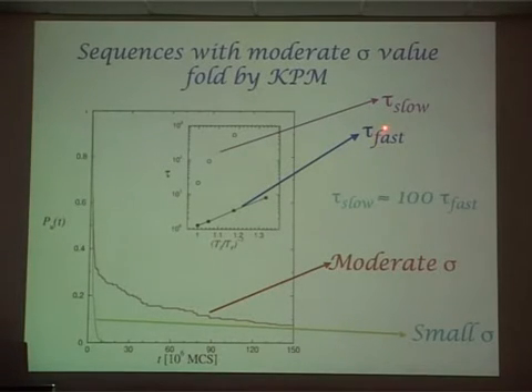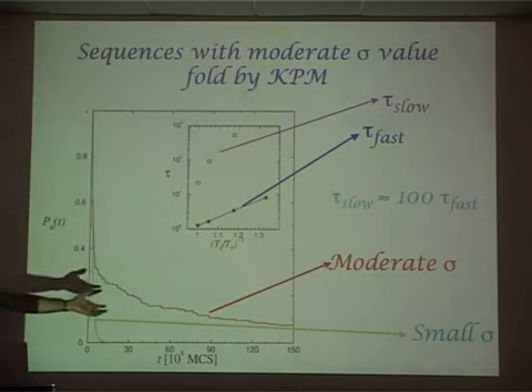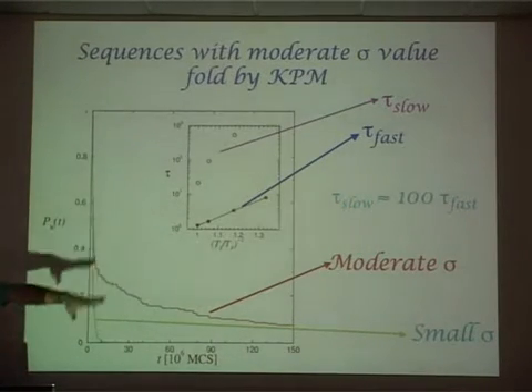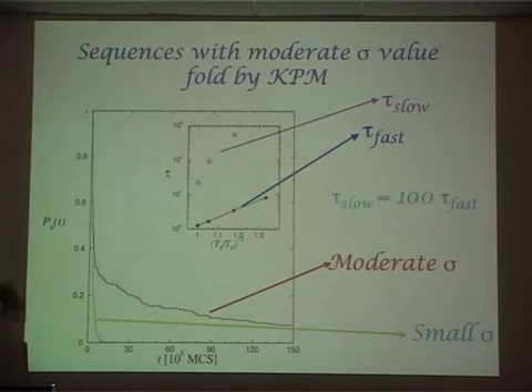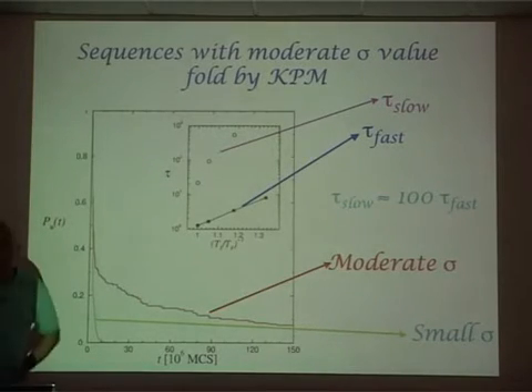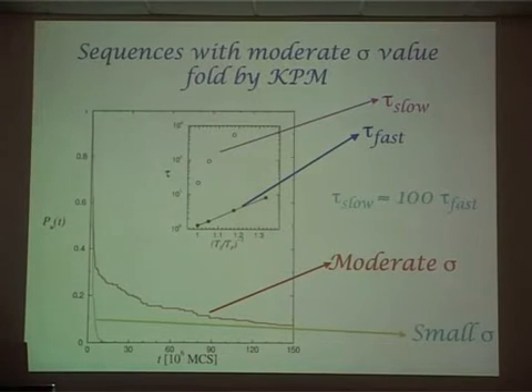So if you look at the second sequence, in which there are only a small fraction of molecules that actually fold rapidly to the native state, whereas most of them fold by this slow track. And you can, in fact, this is a computer, you can calculate the time scales for both. What you find is that the time scales required for the slow trajectories, ones that get trapped in this competing basin of attraction, requiring thermal fluctuations to go to the native state, that time scale is about 100 times slower than the fast track processes. Okay?